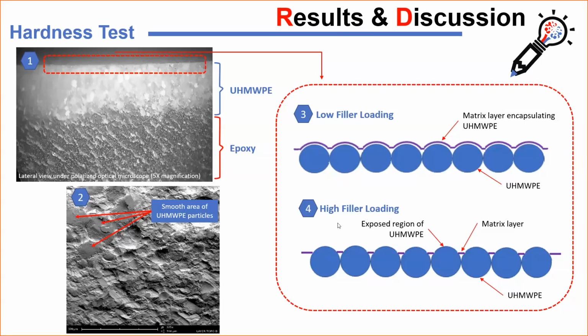When subjected to hardness testing, the value slightly decreased due to the exposed regions of ultra-high molecular weight PE, which possess lower hardness compared to epoxy. However, from the aspect of specific wear rate, the exposed regions of ultra-high molecular weight PE contribute to reducing the specific wear rate by lowering the friction between the composite surface and the steel pin.